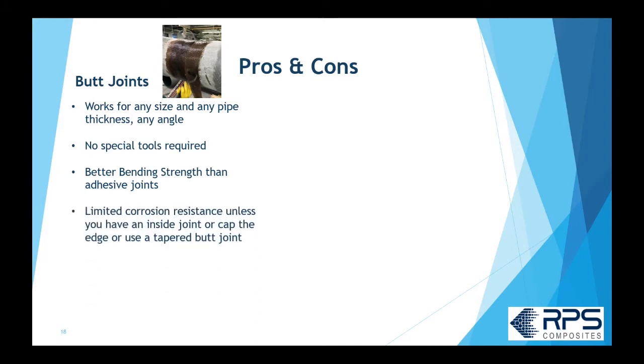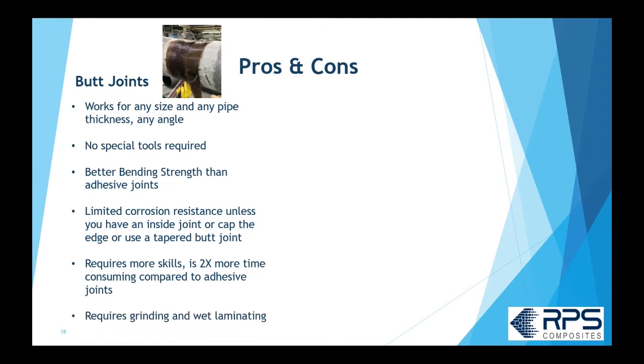You do have limited corrosion resistance with a butt wrap joint unless you cap the end or unless you use a tapered butt joint system. You can see in the video it requires more skill probably to do the butt wrap joint, and it is more time consuming, rough and dirty, about twice as much time as an adhesive joint. And it does require a lot of grinding and wet laminating. You can see when he was removing the gray brush coat, it's a lot of grinding. You definitely need a dust extractor or you're going to have a mess on your hands. And you will have resin, catalyst, and probably acetone on site.